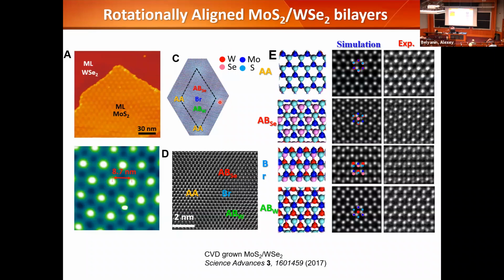So now, because the lattice constant is different, you still have a superlattice. Maybe at what I call the AA point, the top hexagon is perfectly aligned with the bottom hexagon, but because the lattice constant is different, I move away by tenths of a unit cell. Now a different atom in the bottom layer starts to stick out in the center of the top layer. So I can have these high symmetry points that I call AA, AB selenium, AB tungsten. They are represented by the top, second, and bottom. The atomic alignment at these three points still maintains threefold symmetry, meaning I can rotate it by 120 degrees and it would just fold back on itself.